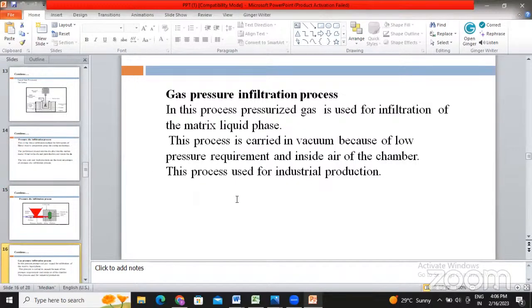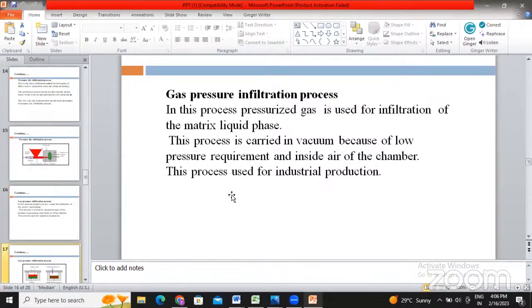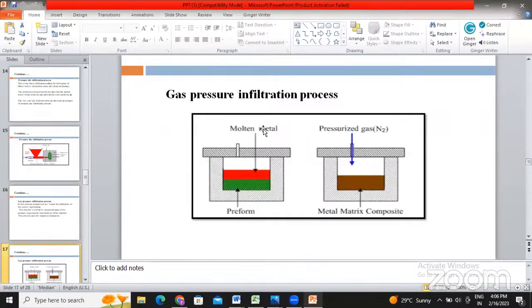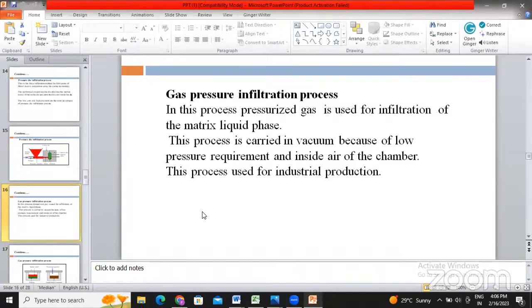Gas pressure infiltration process. With the help of the pressure of a gas, we can also develop the composites or a pellet, and that is the type of arrangement we use here. The molten metal is here, the preform is here. After that, the metal matrix composite is developed by pressing the gas. But the gas should be a neutral gas. And next will be the gas pressure infiltration process. In this process pressurized gas is used for the infiltration of the liquid metal matrix phase. This process is carried out in vacuum because of the low pressure requirement and the air inside the chamber. If you want to do industrial production of the composite, then we can easily use the